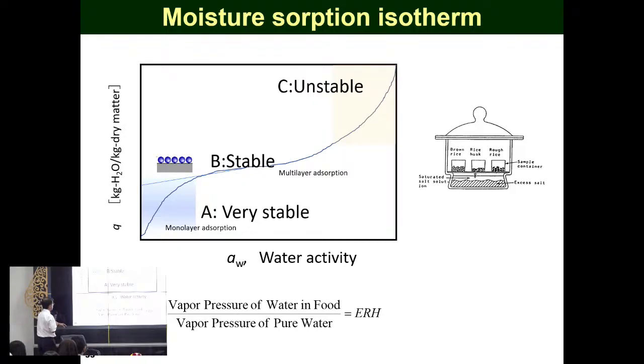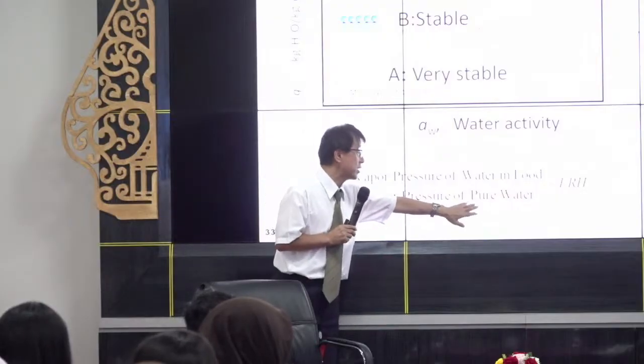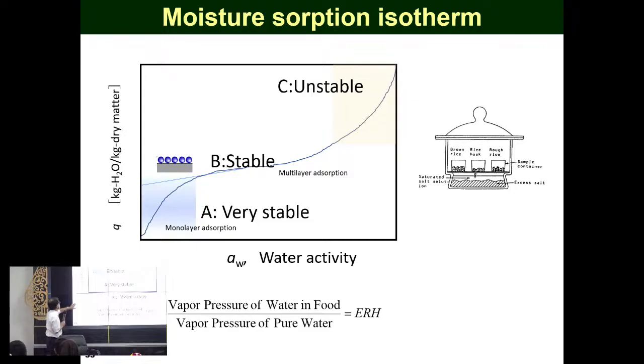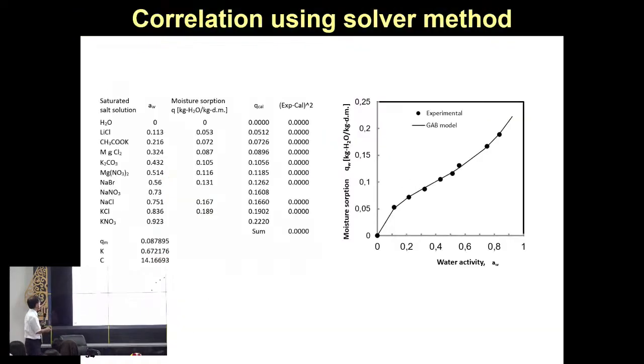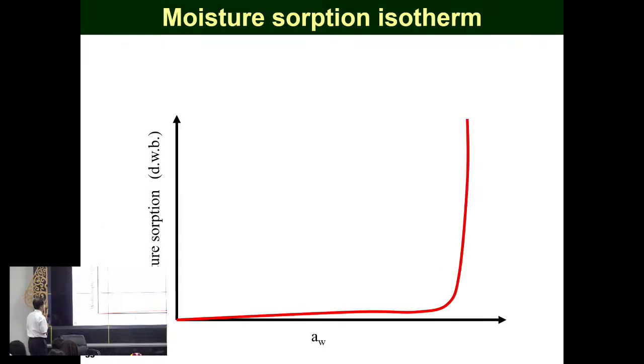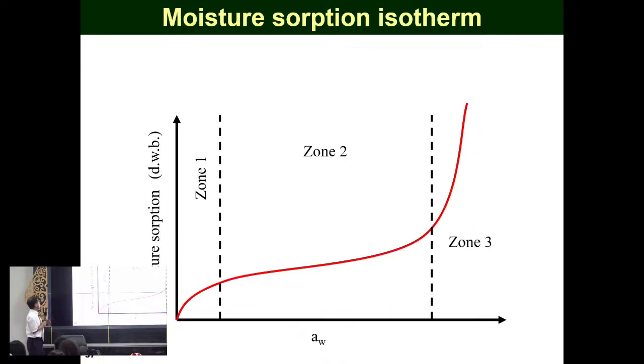So Aw means the ratio of the vapor pressure of water in food to the vapor pressure of pure water, like relative humidity. In the monolayer adsorption region, the powder is very stable and free flowing. This region is also stable, but in high humidity conditions, high water activity, the powder is very unstable. Sometimes you can get this kind of curve by experiment. For some salt, sodium chloride, you get this kind of curve. Another type is this kind of curve.